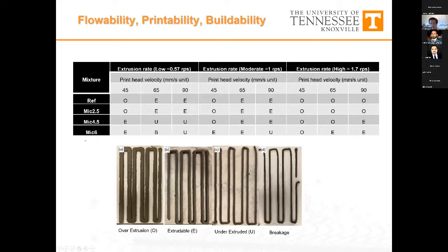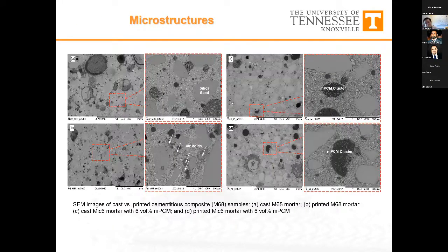With higher volume loading of micro PCM, we found it is beneficial to use a higher extrusion rate and higher printing velocity in this particular case, which makes sense because of the thixotropic behavior of those microparticles. When we talked earlier about those rheology tests, at a higher shear rate, these particles become mobile, whereas at a lower extrusion rate, it becomes much more difficult to extrude.